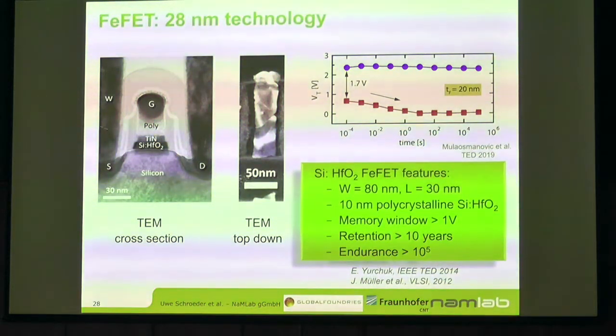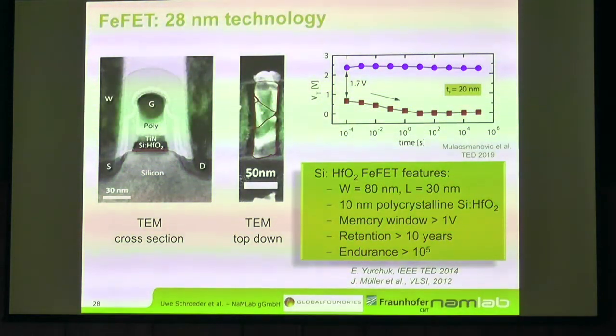They're like 28 nanometer size structures. And if you have a top view of these structures, you can see they consist of just 3 grains. Since the talk is about depolarization fields and the impact of these non-polar phase regions, one non-polar phase is here at the interface between the hafnium oxide and the substrate, because there's always a silicon oxide there, which is non-polar, or it could be that one of these grains is non-polar, and this can also have some impact on your devices.